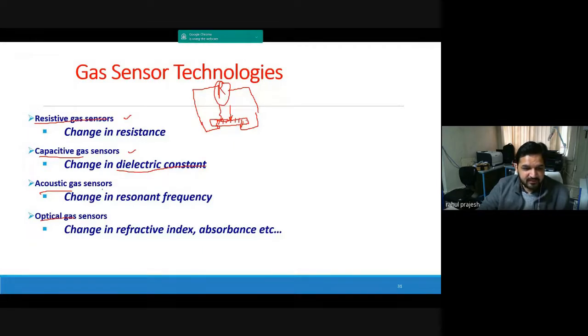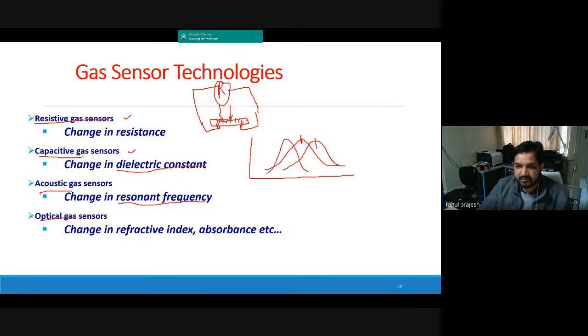Then you have acoustic gas sensor, where you see the resonance frequency shift. So, for example, you have a peak coming over here, and if the gas is present, it will shift towards left or towards right. So, depending on the concentration available, you will get the shift. So, by measuring this shift, you can actually measure the concentration of the gas.